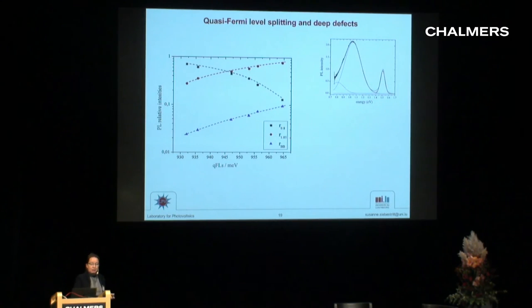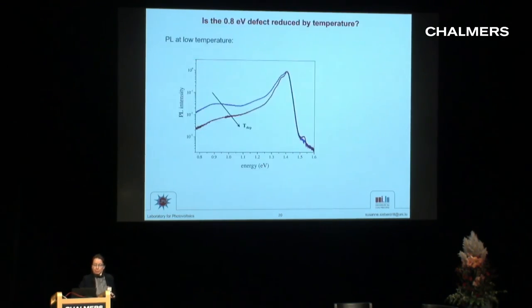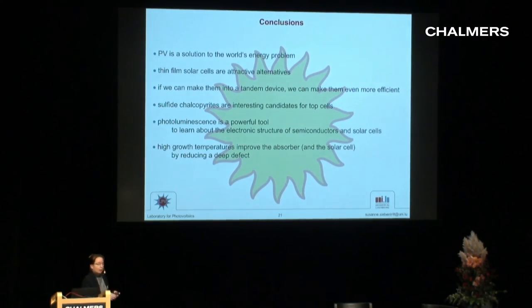And now we measured the quasi-Fermi level splitting as a function of the defects that we saw in the PL spectrum, and we can get a high quasi-Fermi level splitting only when the small peak is low. So it's the small defect at 0.8 electron volt that's the problem, and it's actually there. We see it in low temperature photoluminescence, and I just leave the conclusions there. So by photoluminescence, we can learn something about the semiconductors that helps us to improve the solar cells.